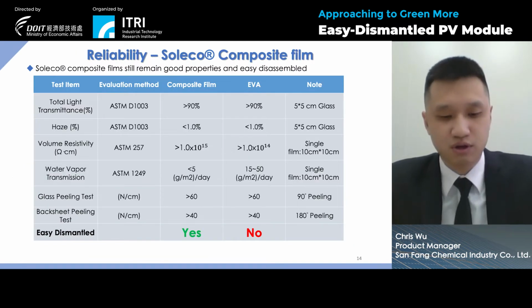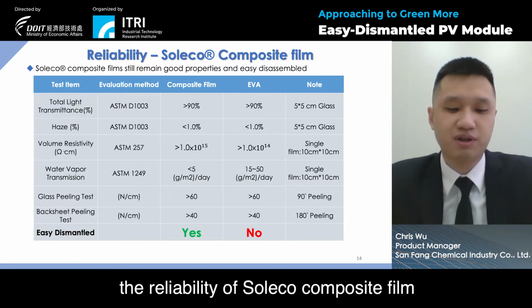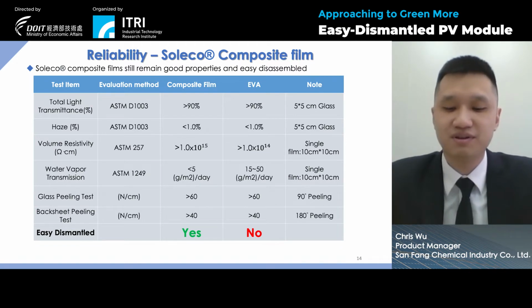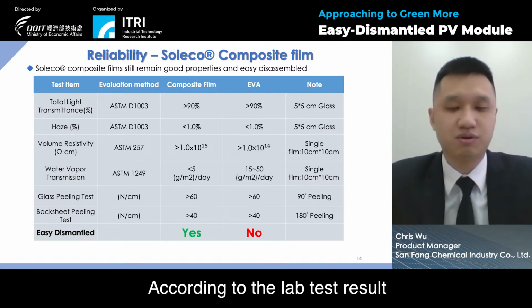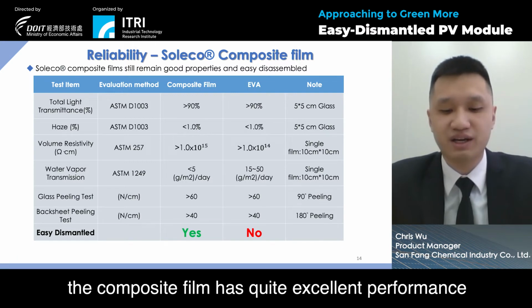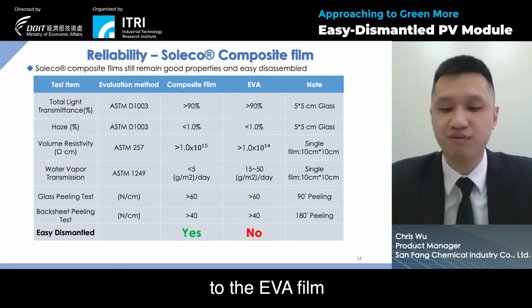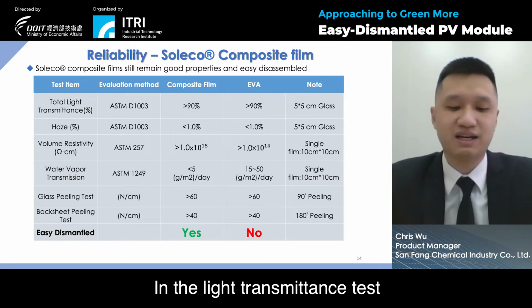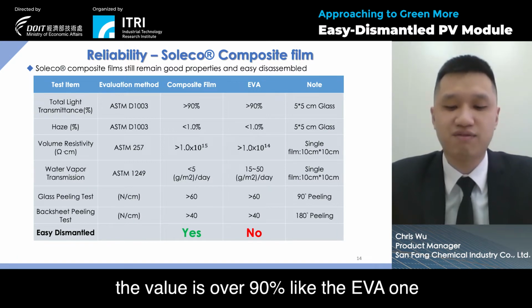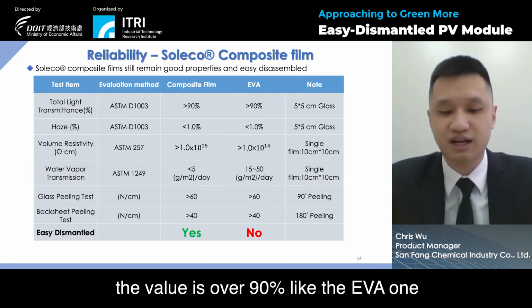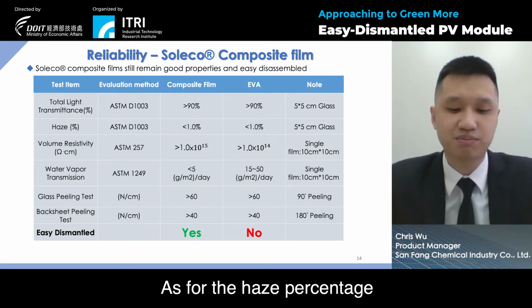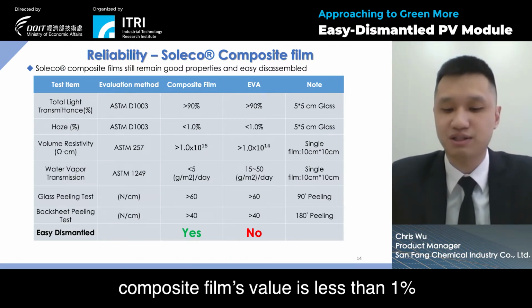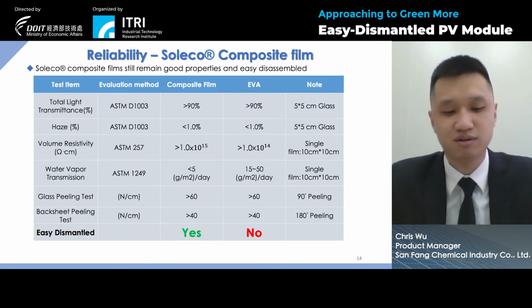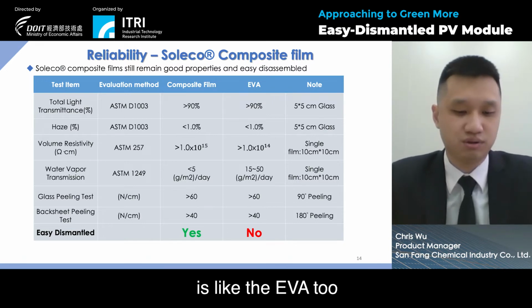Now, also, we have to mention the reliability of the Soleco composite film. Let's take a look at the reliability of the Soleco composite film. According to the lab test results, the composite film has quite excellent performance compared to the EVA film. In the light transmittance test, the result shows that the value is over 90%, like the EVA one. As for the haze percentage, the composite film's value is less than 1%. It's like the EVA too.